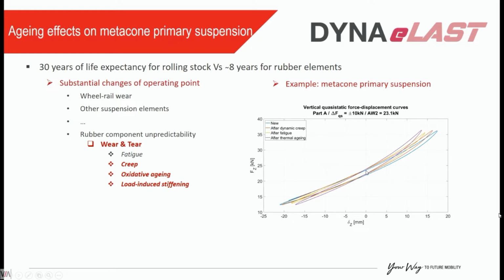What it refers to is this: this is a force-deformation curve of a quasi-static test of a primary suspension. The blue curve corresponds to the new element, the new part, and then we apply cyclic loading. Both dynamic creep and fatigue tests are cyclic loading tests, and what we see is that the element stiffens. Then we put it into an oven and it stiffens further. This last part is what everyone, I guess, is familiar with.